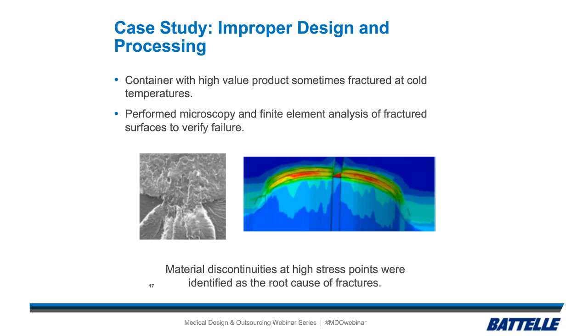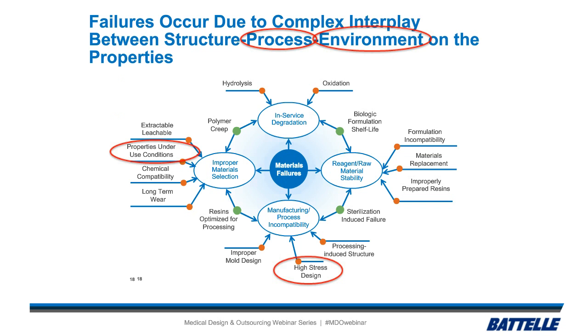The red is high stress, and it's right in that same corner where we saw the highest inconsistency in wall thickness in this polymer container. So when fluid was put in there and then frozen, it would expand when it freezes and put a little bit of stress down on that corner, and when the wall was too thin, it would break. So this one, going back to the chart, we believe was process and environment.